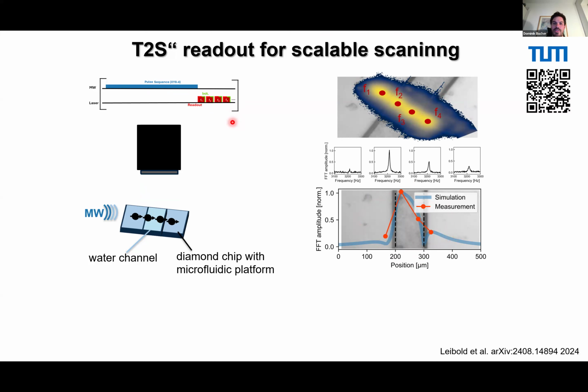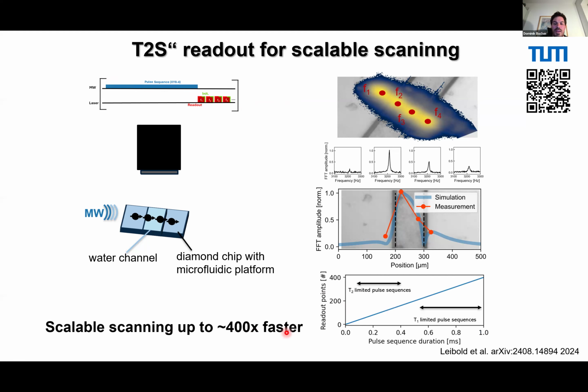But the most important point is you see that you win massively in time because you can get many readouts. So if you keep the readout time the same as your pulse sequence, you can win orders of magnitude. So if you think about a very long pulse sequence on the millisecond time scale, you can accelerate your scanning by a factor of 400. Instead of repeating the pulse sequence, reading out one spot, repeating the pulse sequence, you would apply the pulse sequence on all spins and then do a consecutive time to space encoded readout. So really, I think, mainly due to the simplicity, it's a big advantage for us.